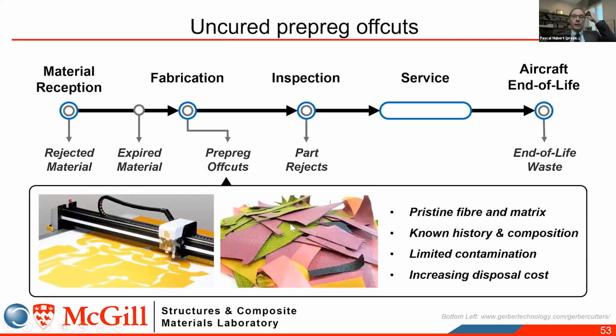So what I really concentrated my effort on was dealing with uncured manufacturing scrap for pre-preg. As I explained in the beginning, our pre-preg comes in the form of rolls, and then we cut patterns. So there are a lot of offcuts from the pre-preg ply cutter. There's also a lot of expired and rejected material. These are all materials that have pristine fibers and matrix. We know their history and how they were stored and processed. There's very limited contamination, and it's going to be more expensive to dispose of these materials. So that's the kind of recycling that I was really interested in developing.